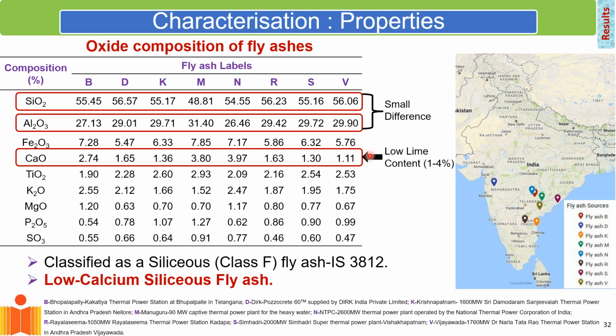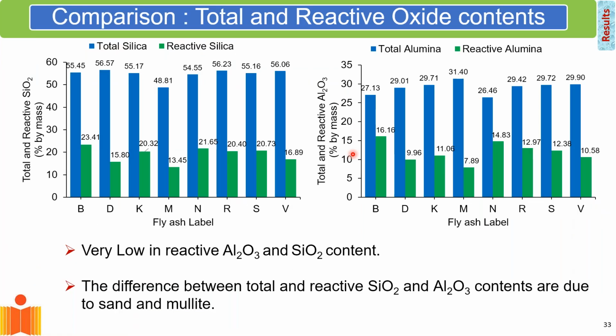But cement is lime rich and this is lime deficient. So basically I'll be reducing the lime content in the system. And we basically developed procedures for determining the reactive silica present in the fly ash. Reactive silica is the silica that is present in that glassy spheres I just showed you.